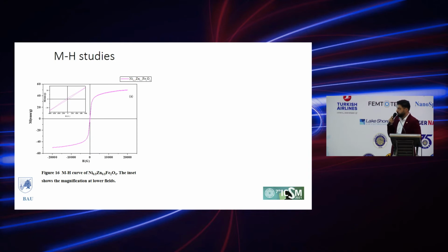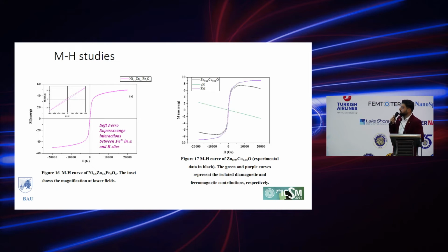Finally, we'll discuss the magnetic properties. For nickel zinc ferrite, room temperature hysteresis curves have shown a soft ferromagnetic behavior. This behavior was explained based on the sublattice Néel model, which assumed super exchange interactions between Fe3+ in both octahedral and tetrahedral sites. For zinc cobalt oxide, the hysteresis loop was deconvoluted into two portions: a diamagnetic portion, which was attributed to surface and ligand effects, and a soft ferromagnetic part, which was explained on the basis of the bound magnetic polaron theory, which assumes a ferromagnetic coupling between the oxygen vacancies and the 3d electrons of the Co2+ ions.